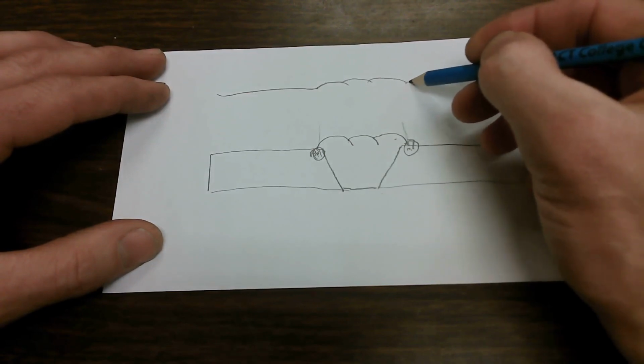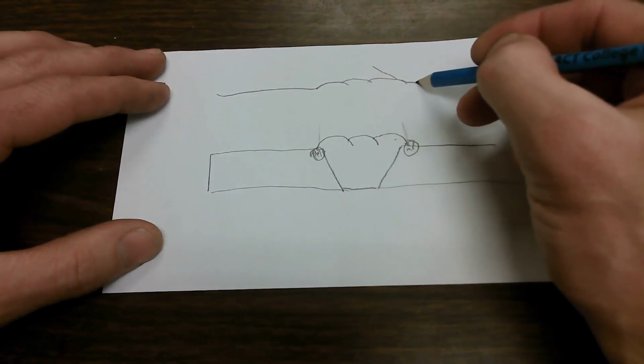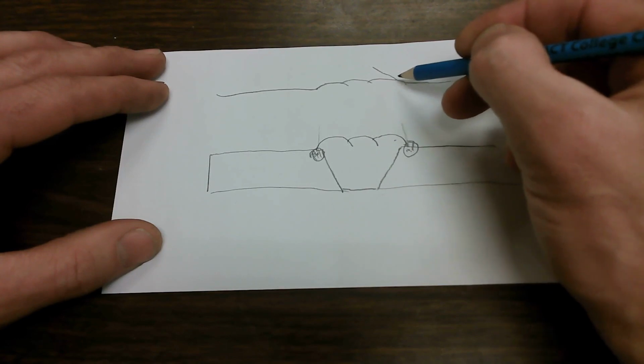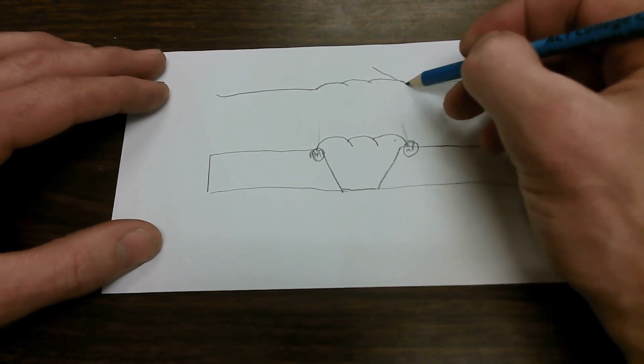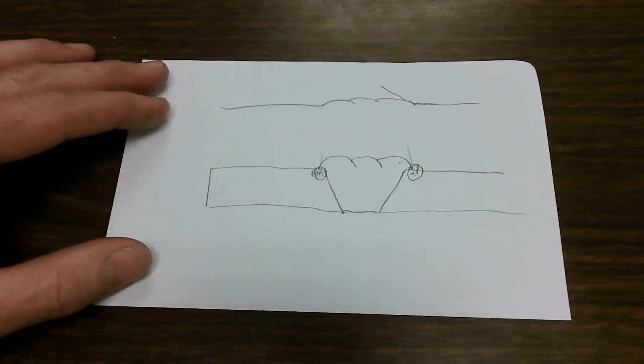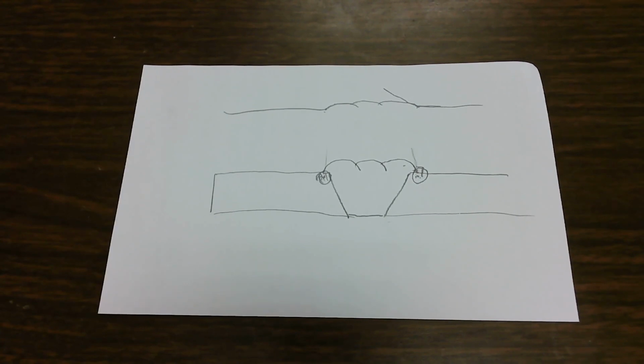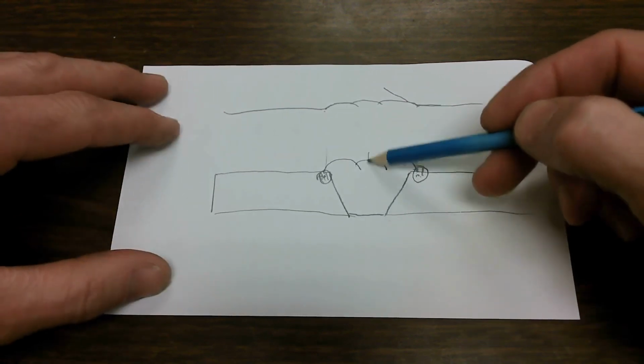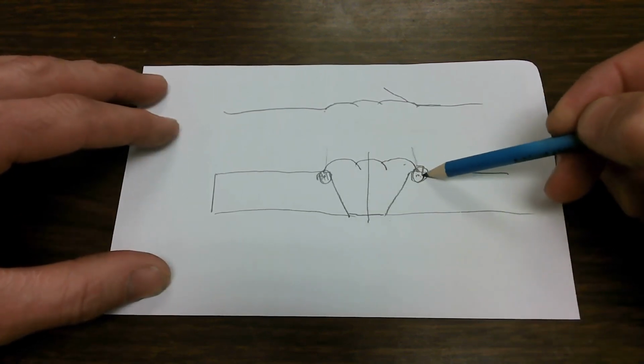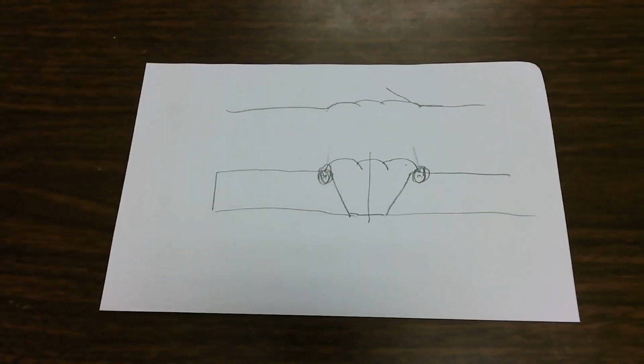The angle is significantly wider up here and more gradual, way less stress accumulating at the toe of the weld. So that's why when we look at a code, reinforcement is kind of a big deal, even though on the surface it seems like it's going to add more strength to your weld. It may add more strength through the throat of the weld, but it adds a lot more residual stress to the base metal right here. So that's why that's in the code, and that's one of the things we look for.